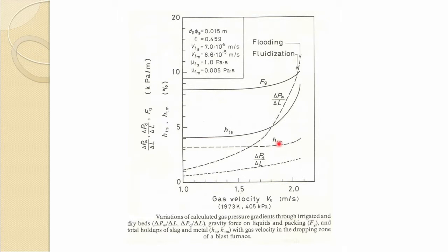And one can see from this that metal total hold up is about 3% and slag hold up is about 4% in the blast furnace, and this has been found by dissection of the blast furnace, which we will see later on. So, the properties which have been used in constructing this diagram: the particle size multiplied with the shape factor is 0.015 meter, bed porosity or porosity in the dropping zone is 0.459, gas velocity is 7 into 10 to the power minus 5 meter per second,